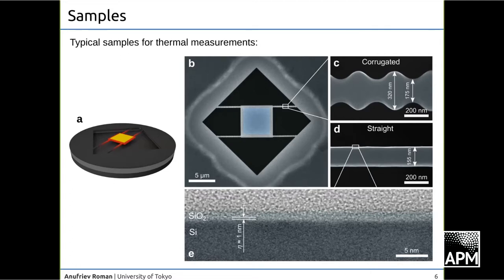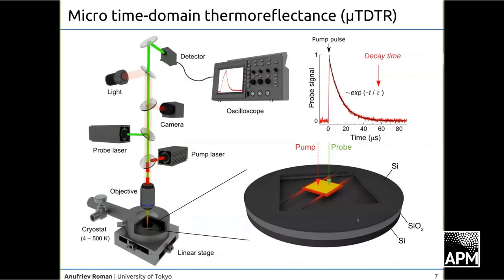So let me show you some experiment. So by the way, yes, we are using micro time-domain thermoreflectance method to probe the heat properties. The method is fairly simple. There are pump and probe lasers that bring the heat to the center of the structure and probe the temperature on this island. And so when the pump pulse comes, the probe signal detects that bump. We heat up this island, and then the heat gradually spreads through the island to the heat sink.